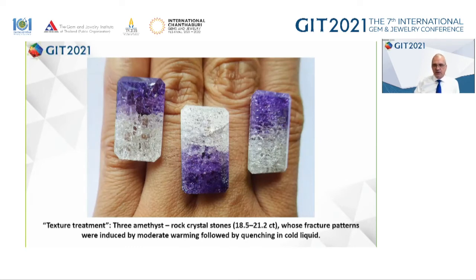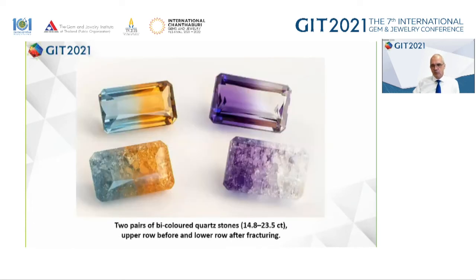There is a huge supply, as I said, of these stones, and some people have started to do some texture treatment with them to make them different from the mainstream stones. Here you can see 3 examples for how these quartzes look after being shocked or quenched in a cold liquid. So they are warmed up a little bit without any effect to coloration, and then they are quenched in cold liquid, and you see the development of an internal fracture pattern. Yeah, so here 2 more examples. In the top row, the stones before, and in the lower row, 2 stones after the treatment.